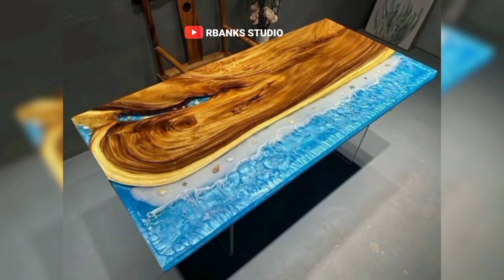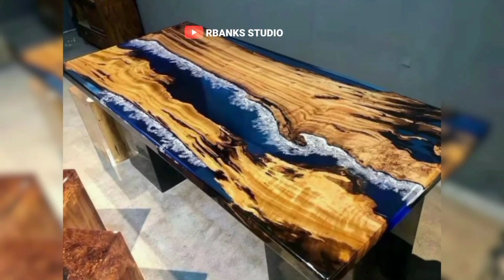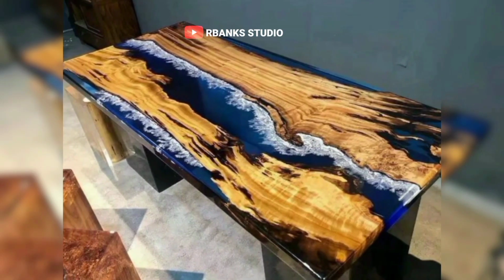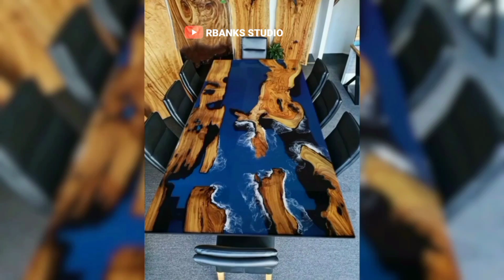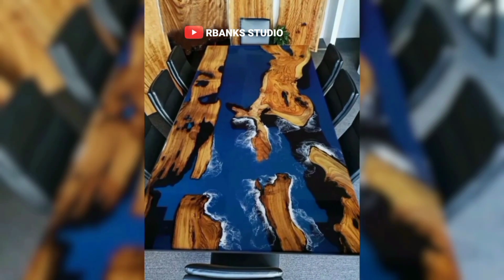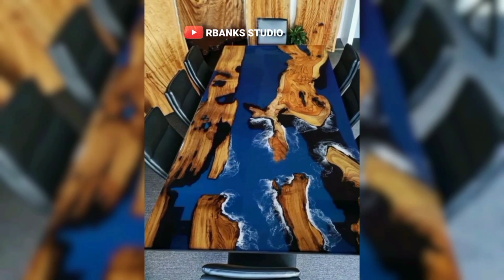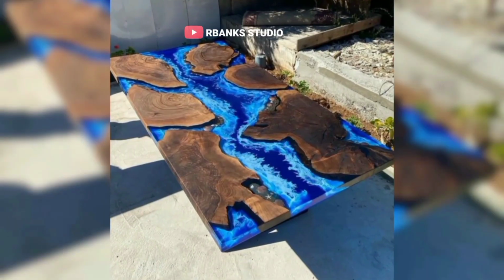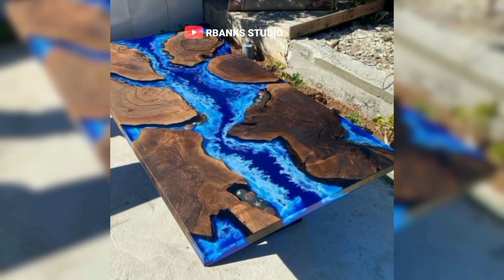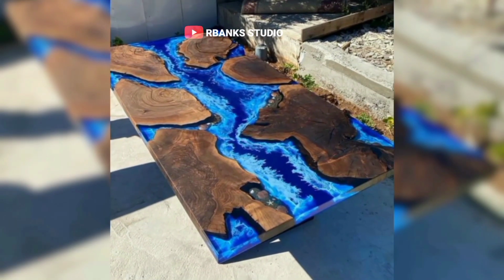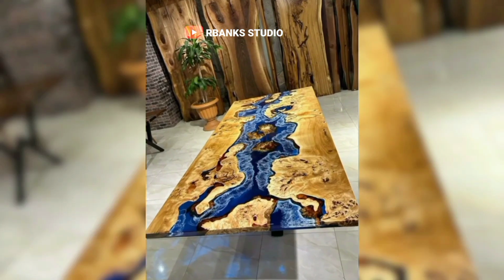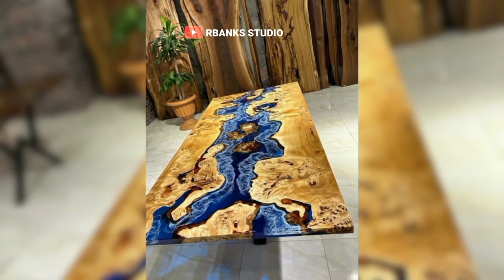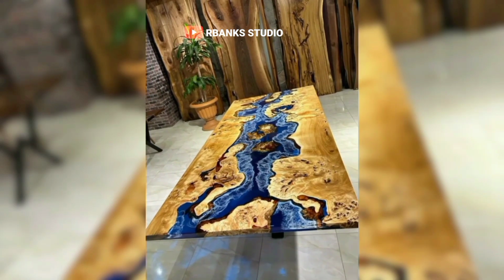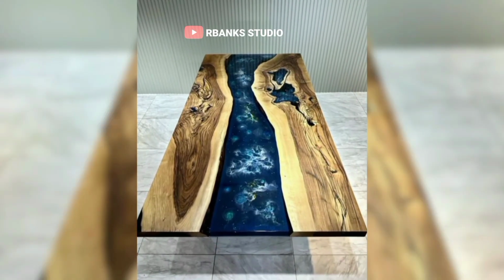After the epoxy has fully cured, I lightly sand the surface with a fine-grained sandpaper to create a rough texture for the polyurethane to adhere to. I then apply the polyurethane with a high density foam roller or a brush, making sure to use long, even strokes. It's important to apply multiple thin coats rather than one thick coat. This allows each layer to dry properly and build up a strong, durable finish.